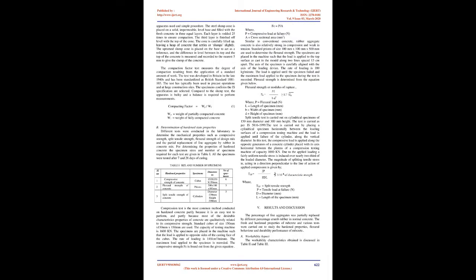In his analysis he found that crumb rubber content in the mix resulted in a decrease in both the slump and unit weight of the mixtures. However, the mix still produced a workable mix in comparison with the control mix. He also reported the reduction in compressive strength, tensile strength and flexural strength, i.e. crumb rubber reduces all types of tested strength.